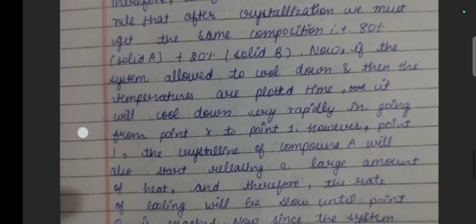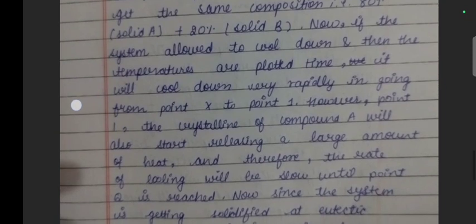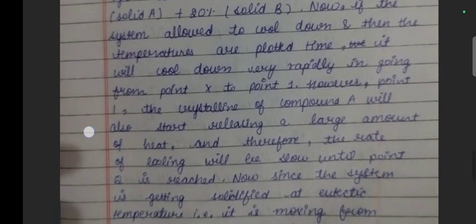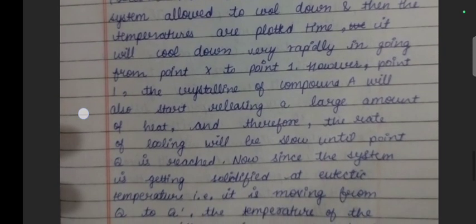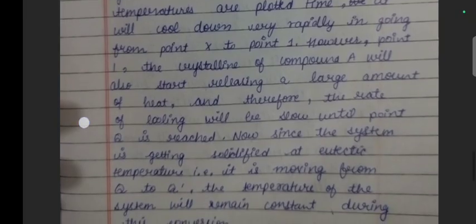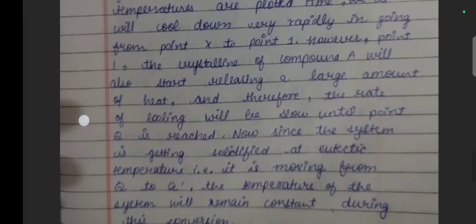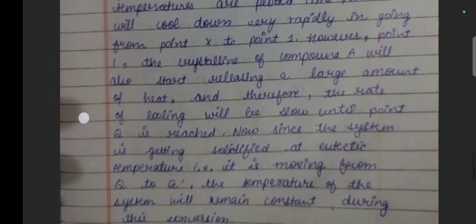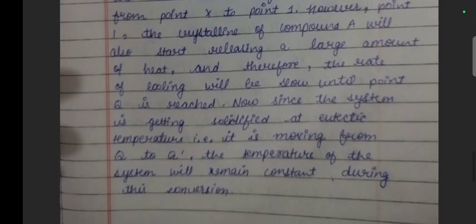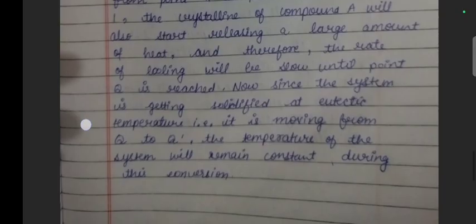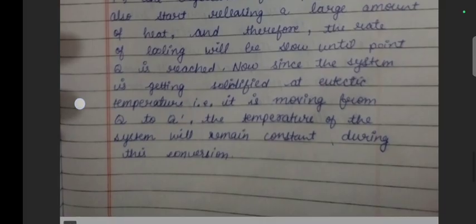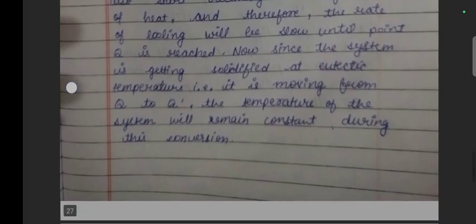Now if the system is allowed to cool down and the temperatures are plotted, it will cool down very rapidly in going from point X to point 1. However, at point 1, the crystallization of compound A will also start releasing a large amount of heat, and therefore the rate of cooling will be slow until point Q is reached. Now, since the system is solidifying at the eutectic temperature, that is, it is moving from Q to Q dash, the temperature of the system will remain constant during this conversion.